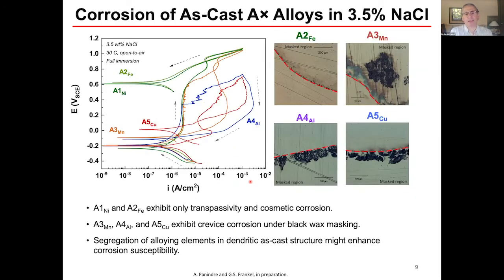Let's look at the corrosion of these samples. These tests were done fully immersed in 3.5% sodium chloride solution. These are the 5 different alloys. I'll tell you that the MPA1 exhibits no susceptibility, as I showed only the upward polarization curve previously. What we see is that when we use nickel or iron to replace, we get essentially transpassivity with a small amount of positive hysteresis coming out of the transpassive region. And in fact, we get some cosmetic corrosion, some small extent of attack.